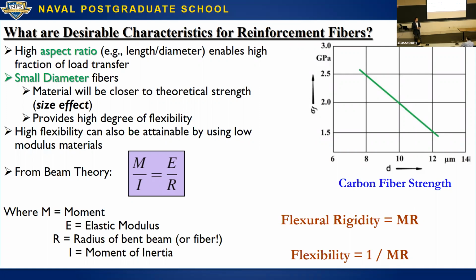Even though we add these ceramic fibers, for example, or even metallic fibers, we know ceramics are generally brittle. When we get very high aspect ratio fibers, it's actually a result just from beam theory, essentially independent of microstructure, that as you decrease the radius of the fiber, you get a much more flexible structure. So you can get very flexible ceramic structures just by decreasing the size. When we deal with classical carbon fibers, you see that as the size decreases, the strength increases quite a bit. That's just a 101 on why we have a desire to make reinforcement particles smaller. You intrinsically get both better strength and the flexibility that you need in a composite.